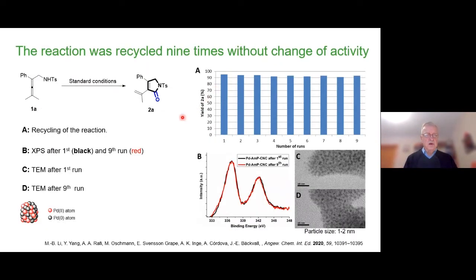And the reaction can be recycled 9 times here, and you see the ninth time we have still a yield above 90%, so it's very efficient. And the XPS here shows that after the first run and 9th run, it's the same. So the red and black here are the 2 after the first and 9 runs. So nothing is happening here.